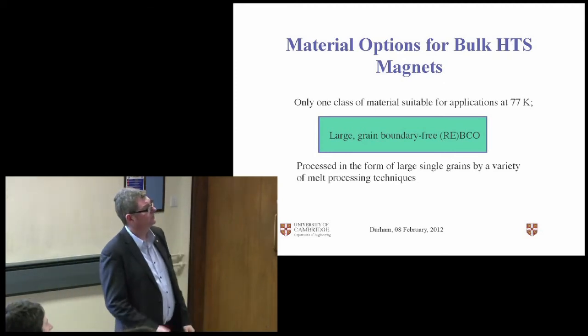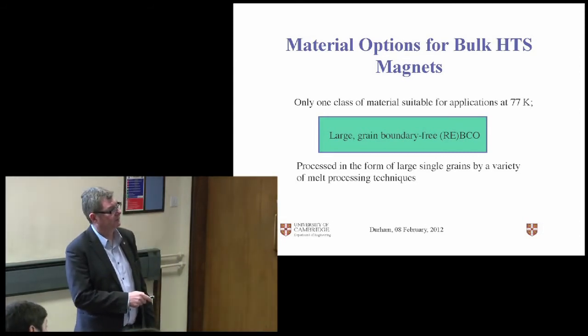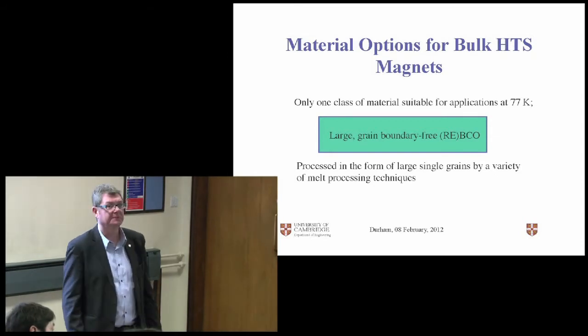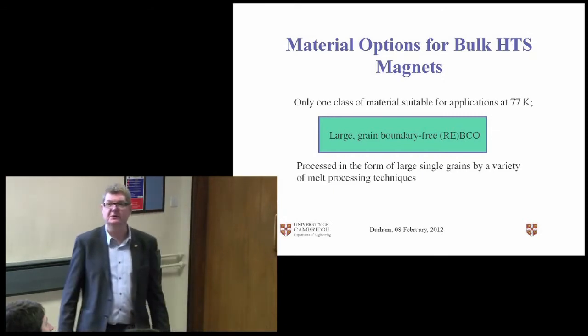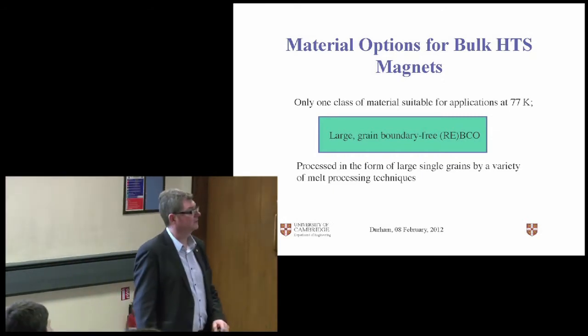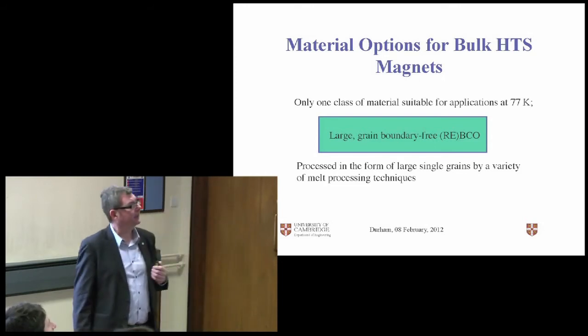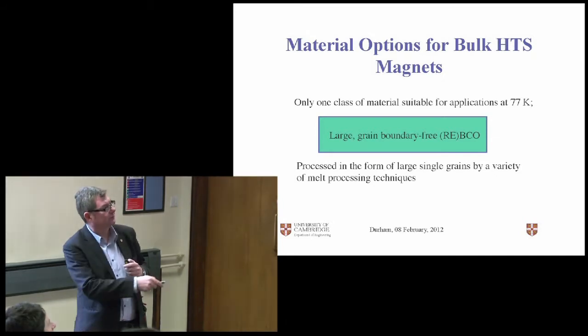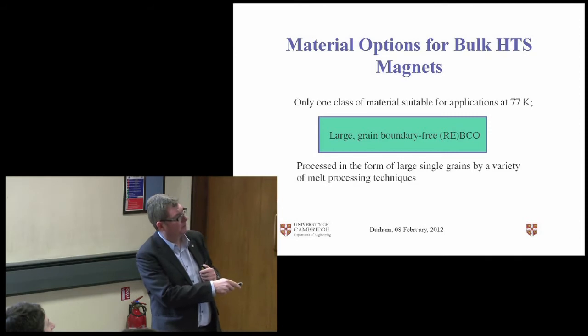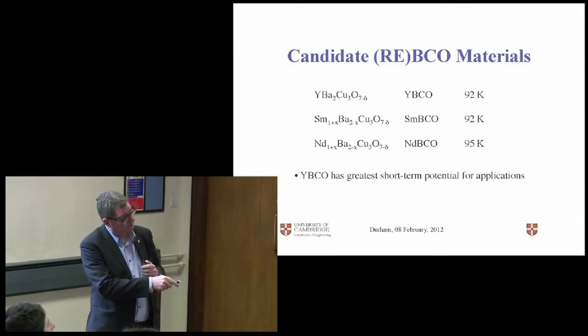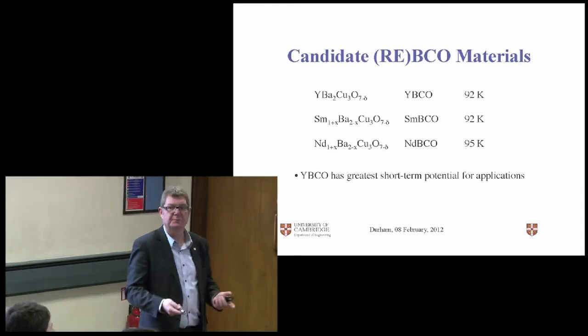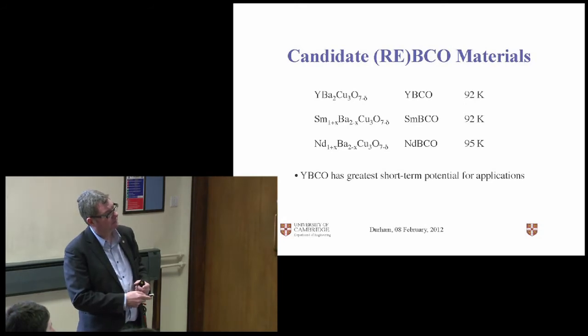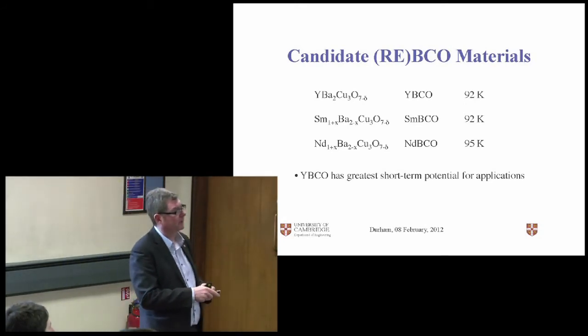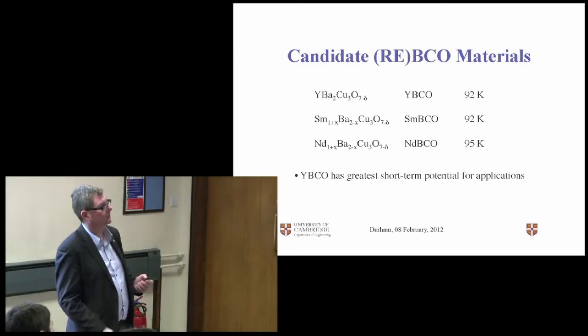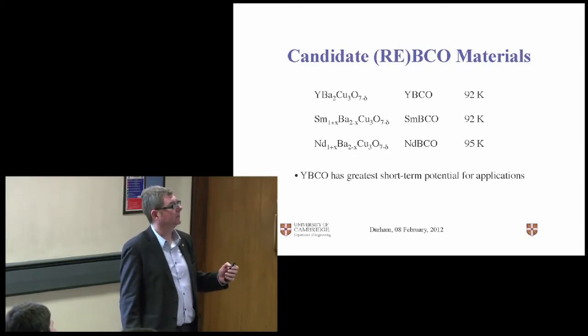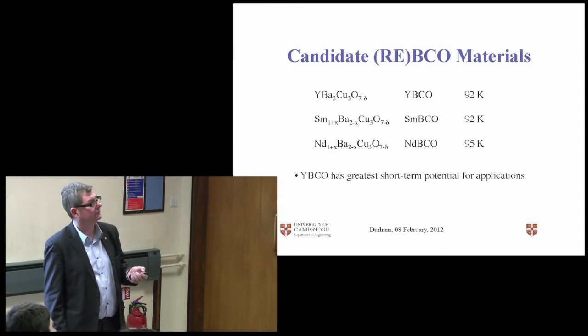So our options are limited. If we want to generate large magnetic fields at 77 Kelvin, we need large grain boundary-free rare earth-bearing copper oxide. And fortunately, there are melt processing techniques available to enable us to eliminate those grain boundaries. We make single grain material. And here are the candidate materials. YBCO, which is straightforward to process. These other rare earth-bearing copper oxides, samarium and neodymium, have got other features, in other words, higher TCs, which give you better properties at 77 Kelvin. But you can see samarium dopes on the barium site, and that reduces TC. And that complicates processing, and I'll mention that a bit later. But YBCO has got the greatest potential for short-term high-field applications. As I said, the first material is still the one that's got greatest potential.